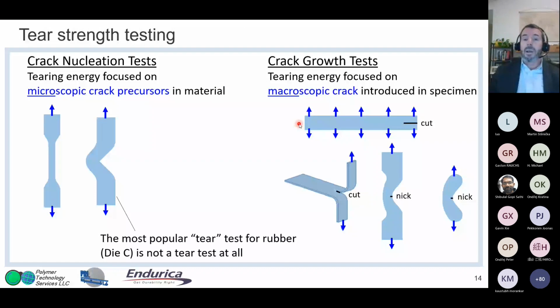There's a variety of ways to test it, but the key way to test this parameter is to put a predefined cut or a nick in the specimen. You have to have a macroscopic crack in order to measure the tear properties, which I always take this opportunity to remind people that the die-C tear, which is very popular in the tire and rubber industry, is not really a tear test. It does not have a nick or a cut. And so it's more like a crack nucleation test. Now, the geometry forces failure in this middle part of the sample, but it is not a true tear test. But a specimen like this planar tension one is very appropriate for making tear type test measurements, as well as the trouser is quite common.